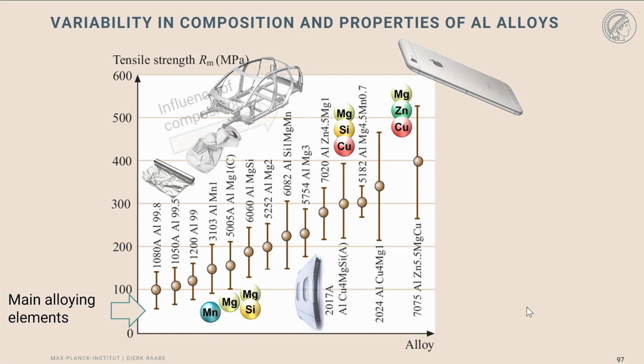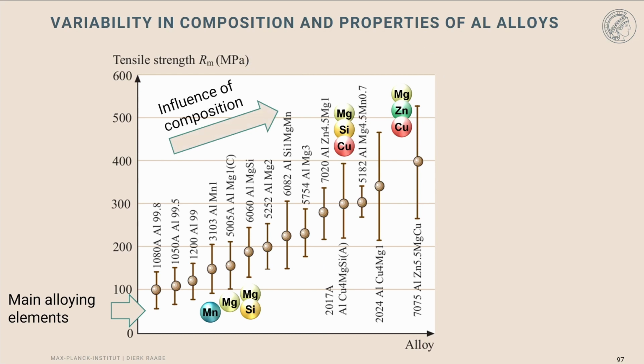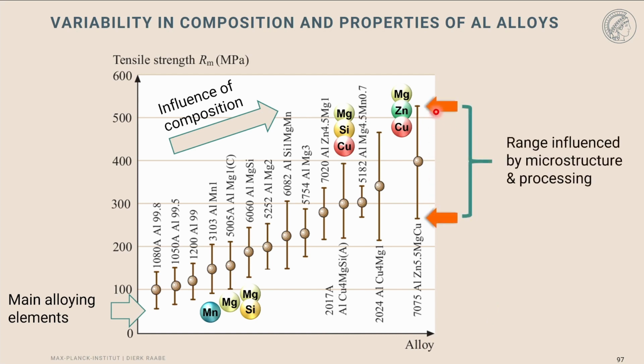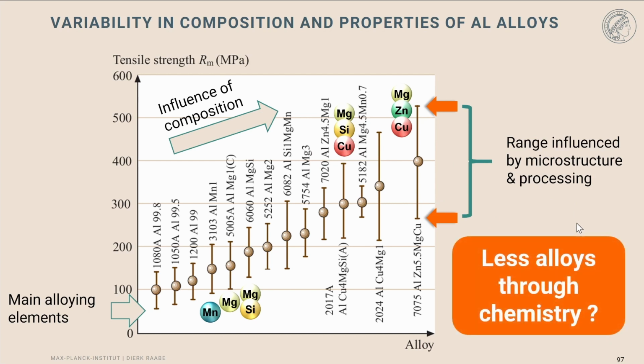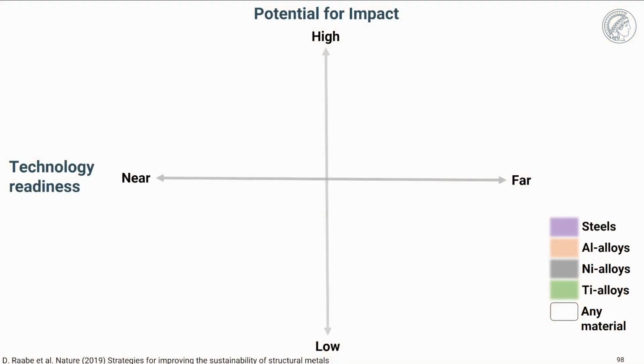And on the one hand, we indeed see a certain clear trend that the tensile strength of these alloys increases with the overall aluminum alloying content. But on the other hand, you also realize that there's a huge scatter for each of these alloy groups. That means there's a big range for the tensile strength in this case that can obviously be influenced by microstructure and by processing. And that means in the future we should maybe try really to design a higher variety of materials, not through chemical variants, but through microstructure variants.